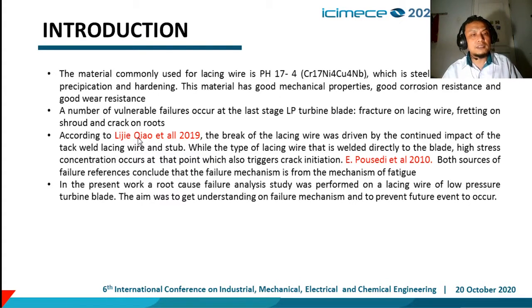But a number of failures occur at the last stage low pressure turbine blade, for example, fracture on lashing wire, fretting on shroud, and crack on roots. According to Lijie Qiao et al., 2019, the break of lashing wire was driven by continued impact of the tack weld, lashing wire, and stub. While for the type of lashing wire that is welded directly to the blade, high stress concentration occurred at that point, which also triggers crack initiation. This is mentioned by Pousedi et al. in 2010. Both failure references conclude that the failure mechanism is fatigue.